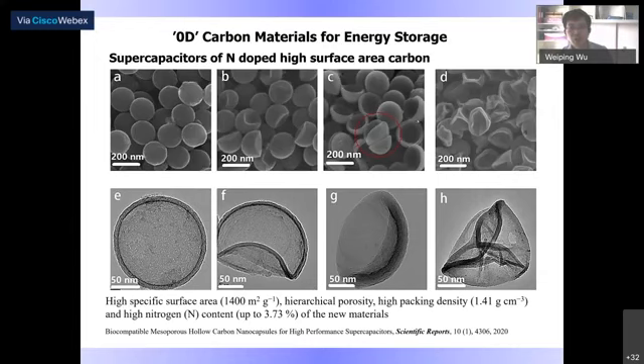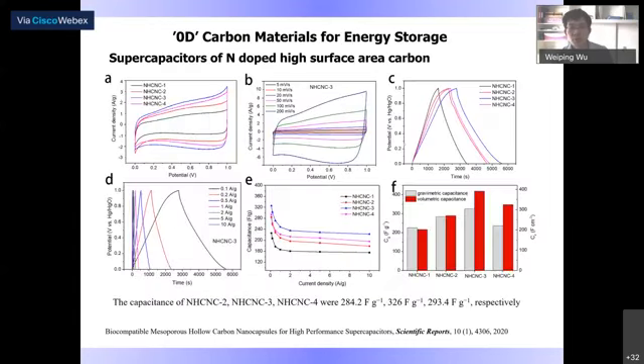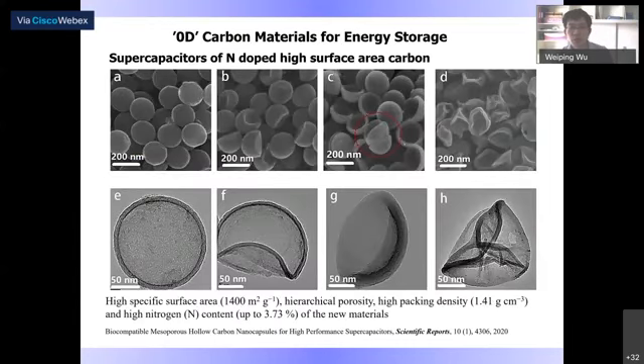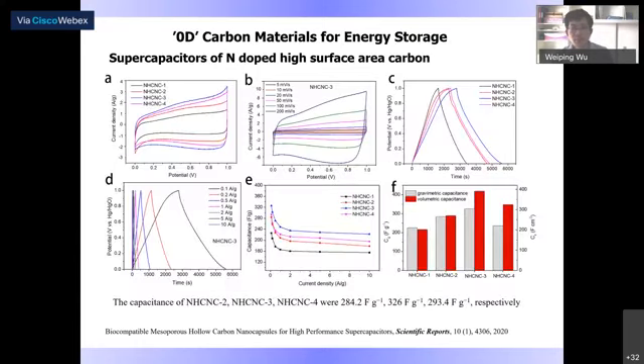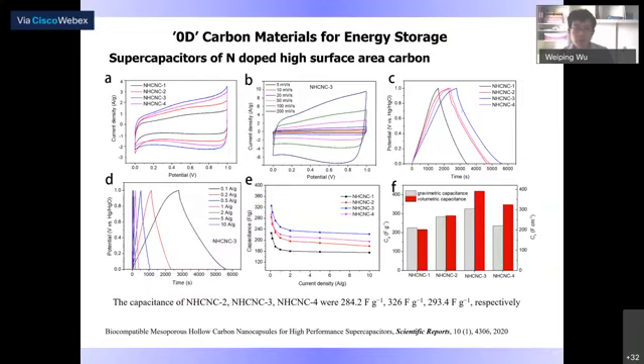So this hollow structure allows me to diffuse the material or electrolyte into the inner space of this structure. Therefore, the supercapacitor performance shows a very interesting trend: these materials show much better supercapacitor performance compared to conventional carbon material prepared under similar conditions.